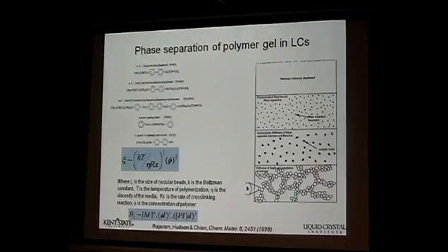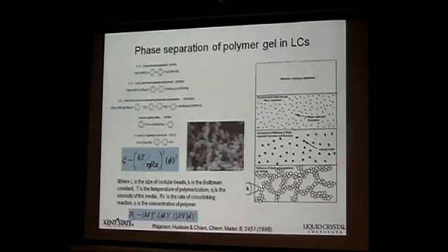Fundamentally, temperature controls everything. Thermodynamics, these factors control the diffusion rate, reaction rate, and so on. Without further consideration, the rate of reaction depends on your monomer concentration, the quantum yield of the light absorption, and the light intensity, if you use light to shine on this material to make the phase separation, and then the cell gap, the path length. You can see that these SEM pictures look like natural, small beads connected together. It can also form fibers if the control of this phase separation is not carefully done.